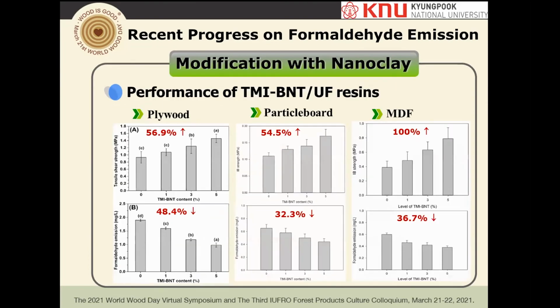So this is what I got from three different wood-based products: plywood, particle board, and MDF. First, the tensile shear strength of the plywood increased about 56% at 5% modified nanoclay. At the same time, formaldehyde emission decreased about 48%. The particle board also has increased adhesion and internal bond strength, and formaldehyde is reduced about 32%. MDF has almost double the internal bond strength, and about 36% formaldehyde reduction.